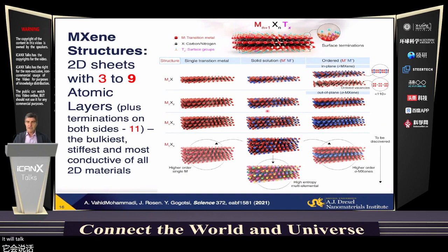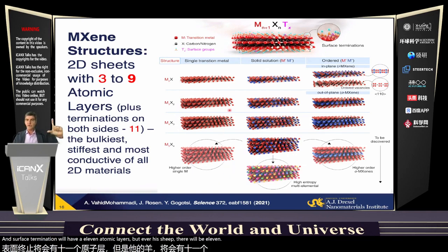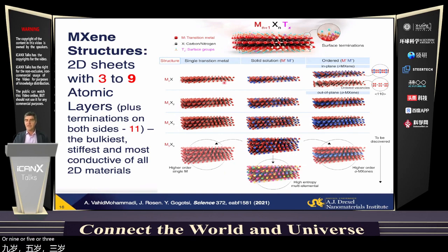People talk about graphene, telling, look, this is the thinnest material available. MXenes are at the moment actually the thickest 2D materials available. This material with 5 layers of transition metal, 4 layers of X element, and surface termination will have like 11 atomic layers, but every sheet will be 11 or 9 or 5 or 3 layers of atoms thick here. So we have discrete change in properties. We have all flakes of the same size, single crystals, but they add stiffness, they add stability of conductivity.